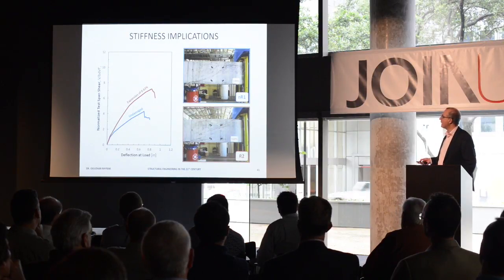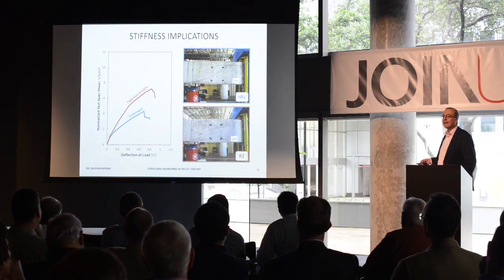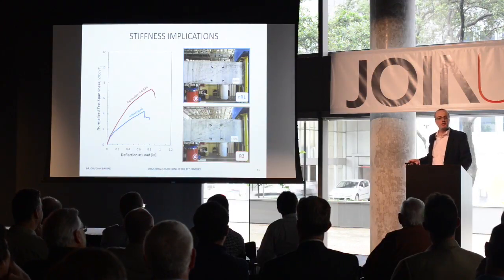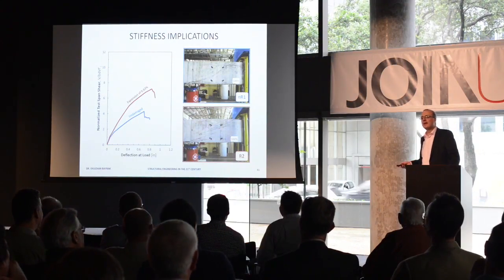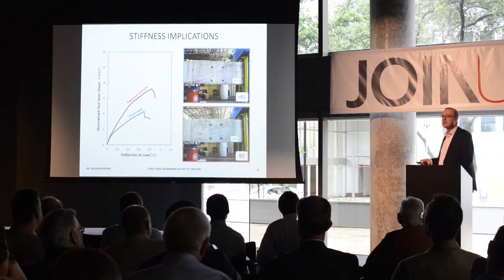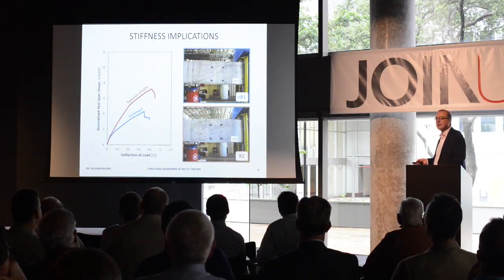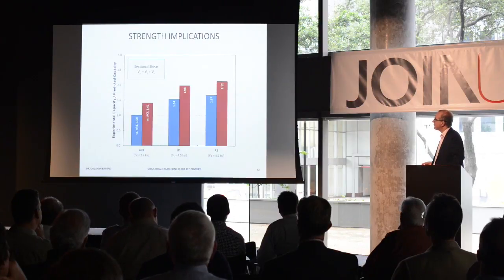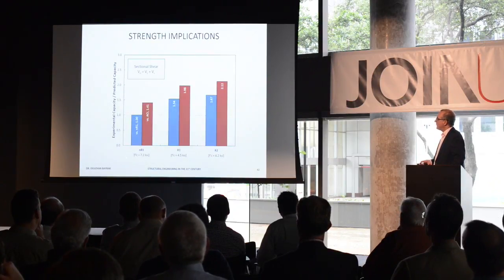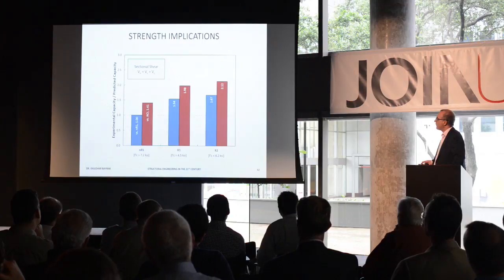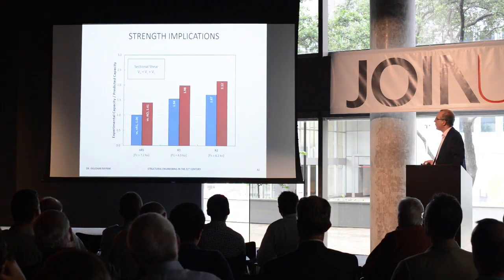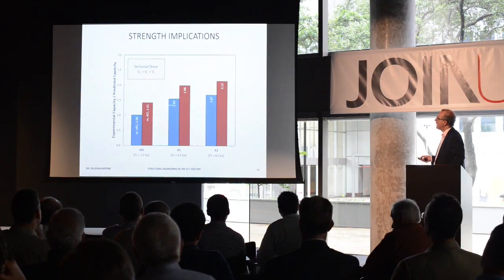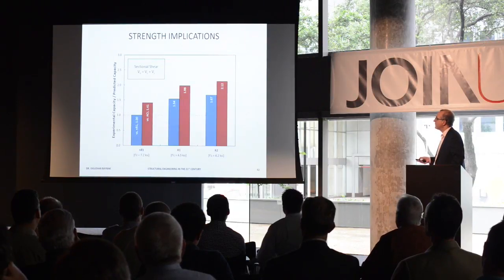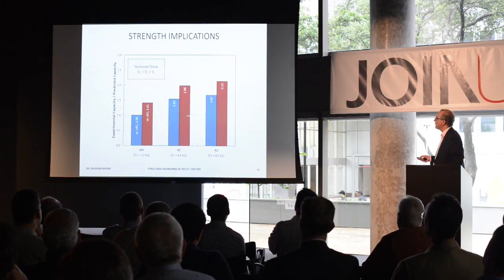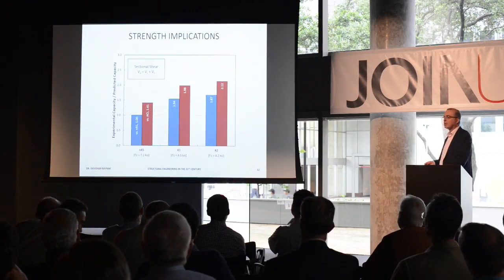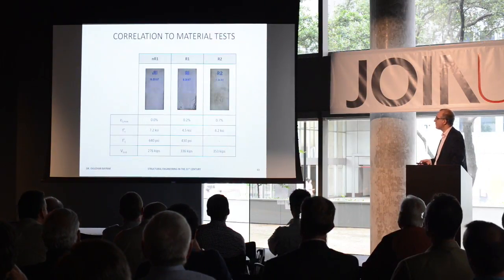Certainly we're not going to say that ASR is great. Try to build it in your structures and it improves capacity. In the end, we're responsible structural engineers, but I think it's fair to say that the impact is fairly negligible. In a nutshell, when the compressive strength of concrete drops from 7 KSI to 4.5 to 4.2 KSI, shear strength seems to be having a different trend, and you can see the code calculations level here. Certainly it poses about 0 threat.